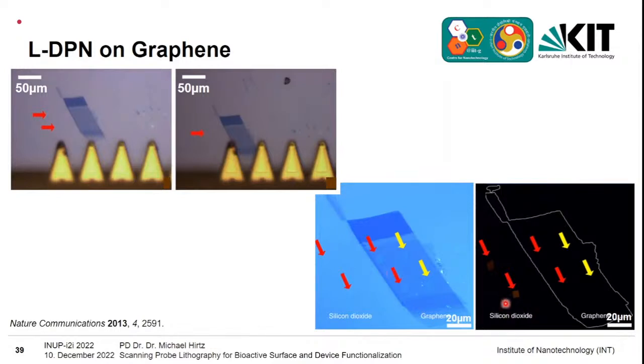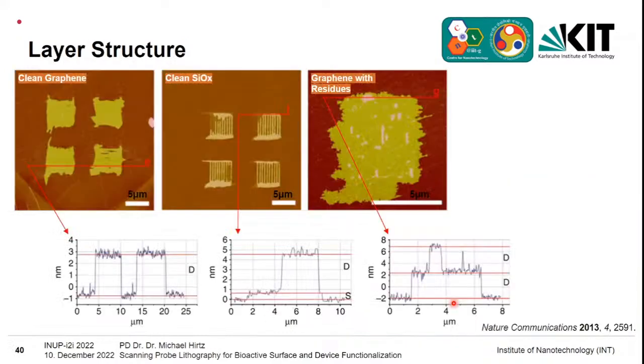You can also here, by the way, see that there is fluorescence quenching on the graphene. So this also tells you that the membrane is in very close vicinity to the graphene and can electronically interact. The fluorophores in the membrane were quenched, and you don't see them in the fluorescent microscope anymore, while they're for sure here.